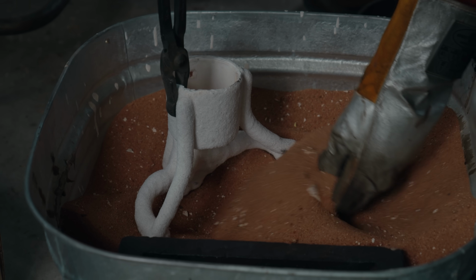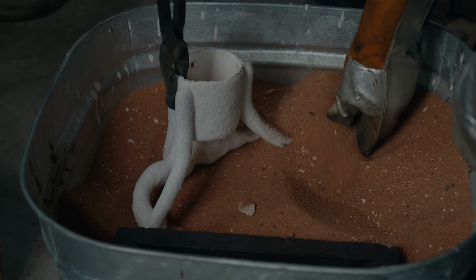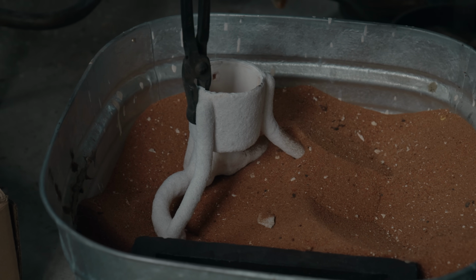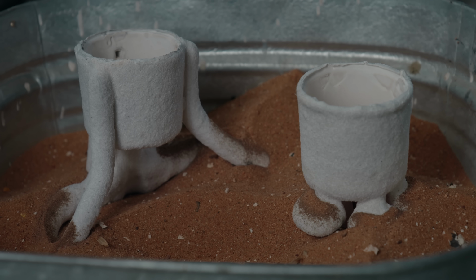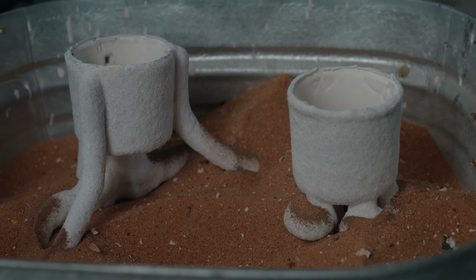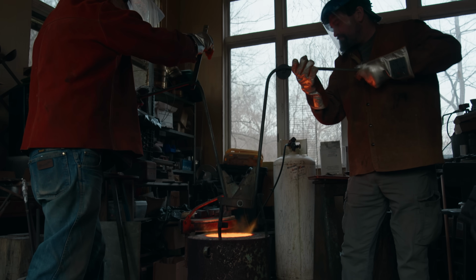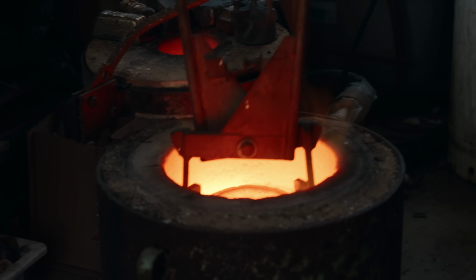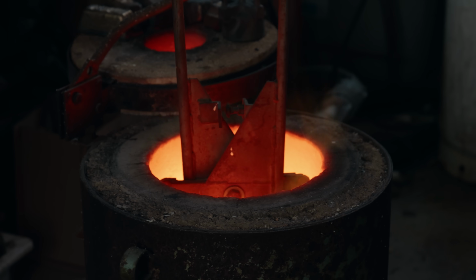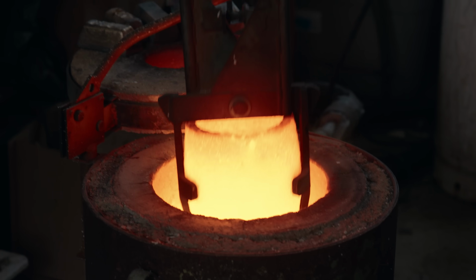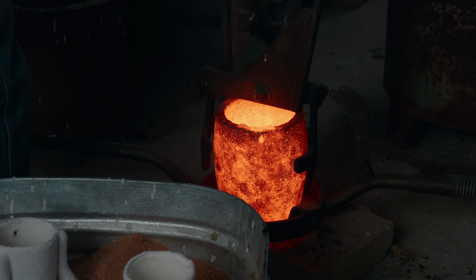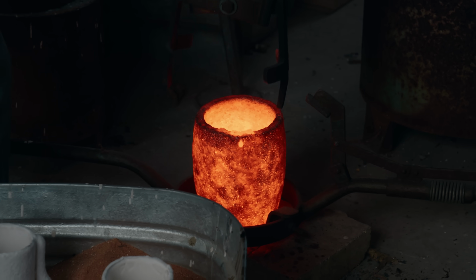Now that this slurry has created a mold on the outside of our pattern, it will have to be fired. We're going to put it into a preheated kiln at 1600 degrees. That's both going to harden and cure the outside of the mold and burn away all of the plastic resin that's on the inside. That's going to leave a cavity where, of course, we can pour in bronze.